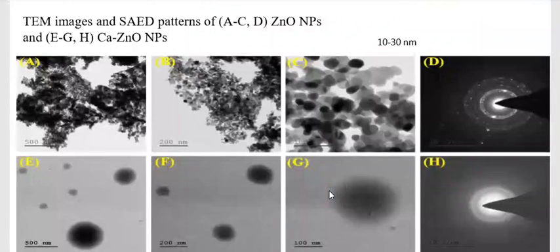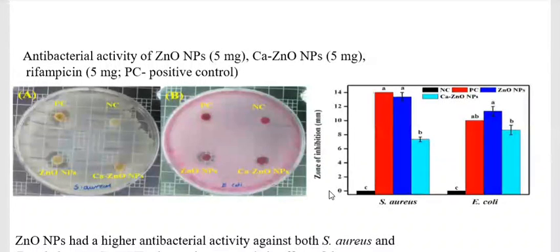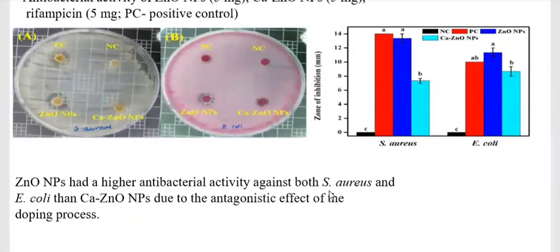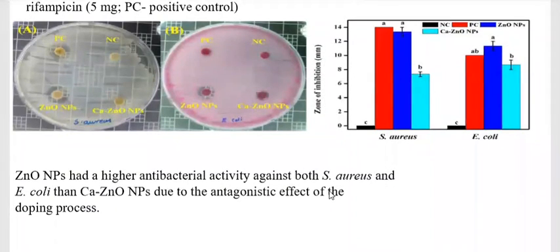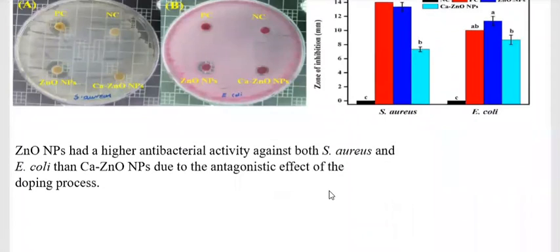So these were tested for antimicrobial activity at 5 mg against gram positive and gram negative bacteria, Staphylococcus aureus and E. coli. At 5 mg concentration, zinc oxide nanoparticles show a better response compared to the calcium doped nanoparticles, because with calcium doping the antimicrobial activity decreases. The negative control used DMSO, and the positive control used rifampicin, at 5 mg concentration.